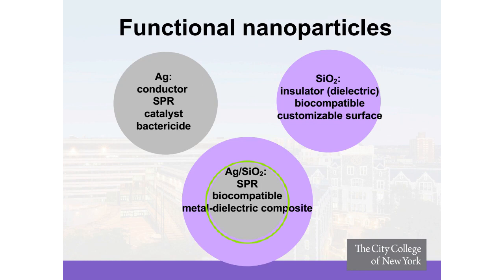Specifically, the material that we have been looking at in the lab is a silver core that is a conductor and can be used either as a catalyst or as a herbicide or a bactericide. We're using a silica insulator shell that also can be a titanium shell. It could be also a zirconia shell. And the combination of the two actually allows us to generate a metal dielectric composite.